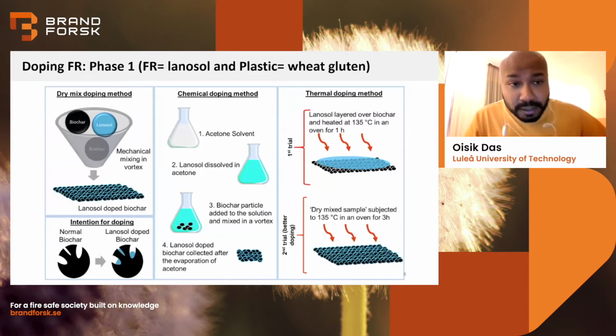The doping of the fire retardant into the biochar was done in 3 different ways. And the whole project was divided into 2 phases. In phase 1, we used Lanosol, which is an algae-based fire retardant. Algae we can derive from oceans. And the plastic used was wheat gluten, which is a bioplastic, extremely sustainable and biodegradable. And we tried to dope this Lanosol fire retardant in wheat gluten bioplastic in 3 different ways.